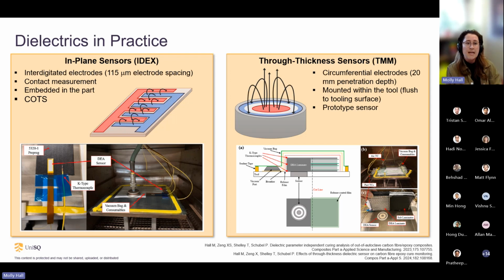They're very well understood. They do tend to get embedded in the part. They can also rest on a surface of the part. But this one we do consider to be a little bit more of an invasive method. They have a very small spacing between the electrodes, and this means that they're really getting a contact measurement of just the surface that they're touching.